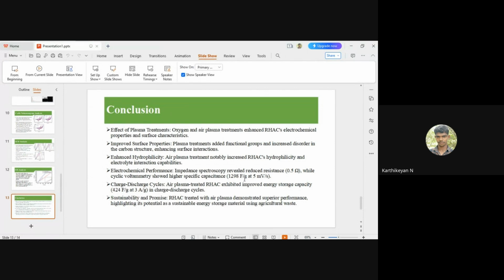For electrochemical performance, impedance spectroscopy revealed reduced resistance, and cyclic voltammetry showed higher specific capacitance of 1298 F/g at 5 millivolt per second. In the charge-discharge cycle, air plasma treated RHAC exhibits improved energy storage capacity of 424 F/g at 3 amps per gram in GCD analysis. Sustainability and promise: the RHAC treated with air plasma demonstrated superior performance, highlighting its potential as a sustainable energy storage material using agriculture waste.